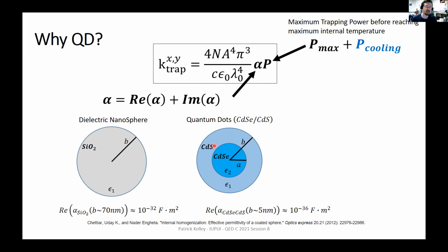For us, we're going to be playing with a cadmium sulfide, cadmium selenide quantum dot, which is going to be of the order of 5 nanometers. And the real interesting part is this imaginary part of it, which is what contributes to how much power of the laser the particle is going to absorb and heat up. So depending on our imaginary part of our polarizability, which depends on our dielectric, that will play a role in how much power we can put into our laser, and of course also have a cooling term as well. So we can put more power, which means a stiffer spring constant, which means a lower temperature.